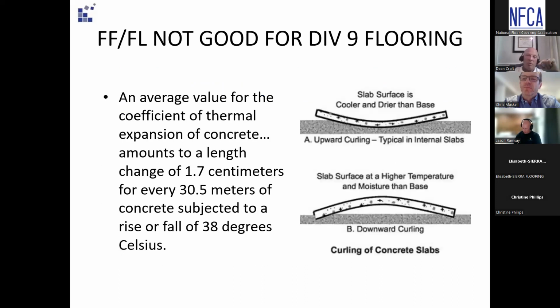So if they're not curing, if you had rapid evaporation, it could cause curling and also a temperature change. So some of the things that you may be facing, especially at your saw cuts, is something like the top right picture. In your area, if they're placing concrete in the winter and they're not protecting that surface to keep it close to being warm, that cold air hits it and you can have your saw cuts be way out of whack. On a project we're on right now, it's a full inch of saw cut elevation. They passed their FFL in December, and now the saw cuts are all raised up, and everybody's floundering. Oh, I don't understand why, because the concrete wasn't protected after placement.